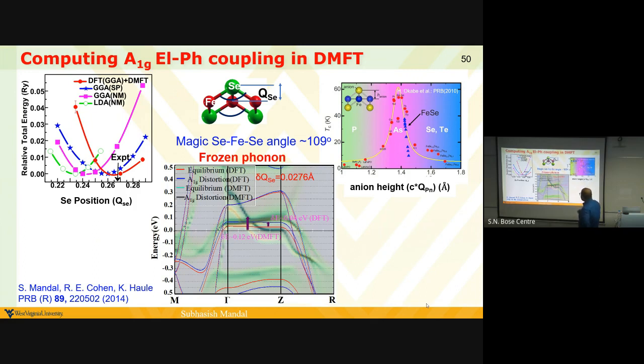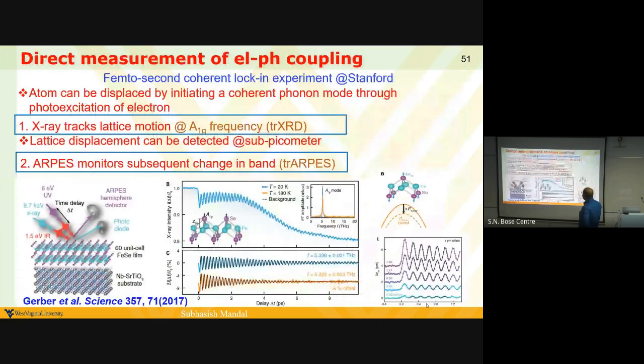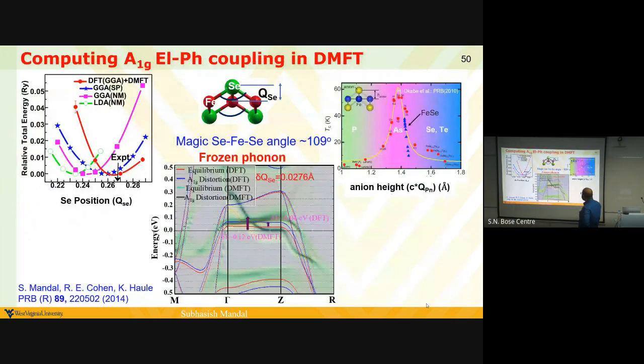So this is just a pictorial view. Ideally, it is done on a very large scale mesh and around the Fermi energy, and you see the shift. We actually found this one order of magnitude higher value, and we got excited, sent it to PRL, and then they said everything is good, but do not care about phonon, because this is not a phonon mediated superconductor. And then it appeared in rapid communication.